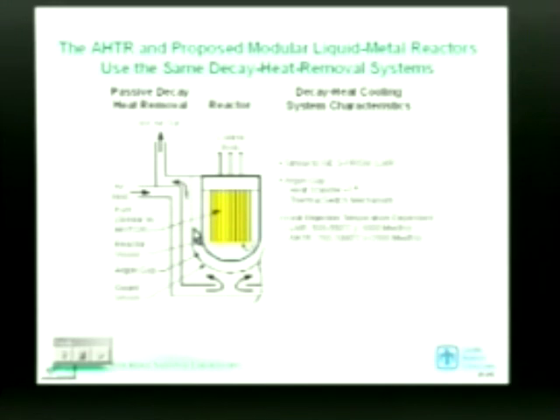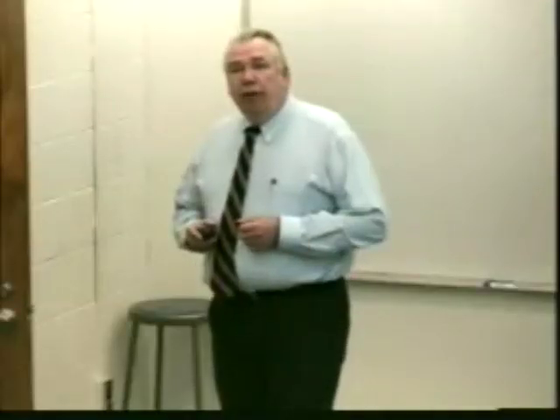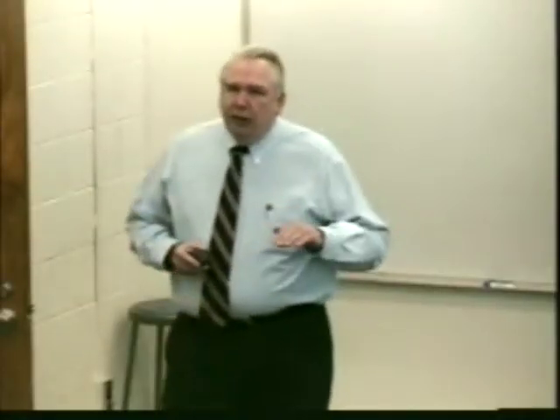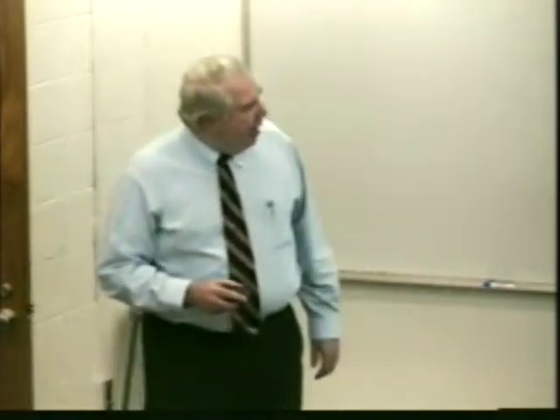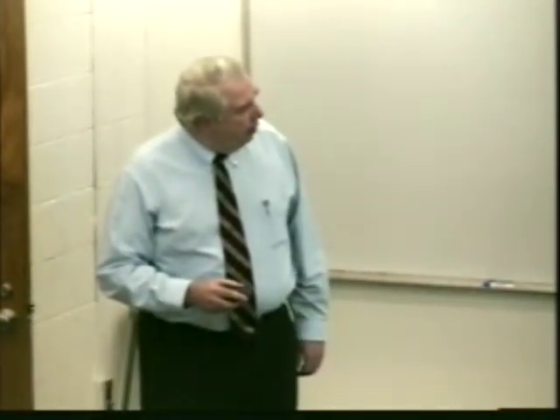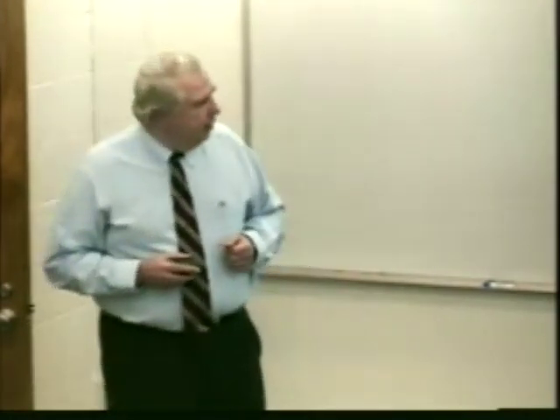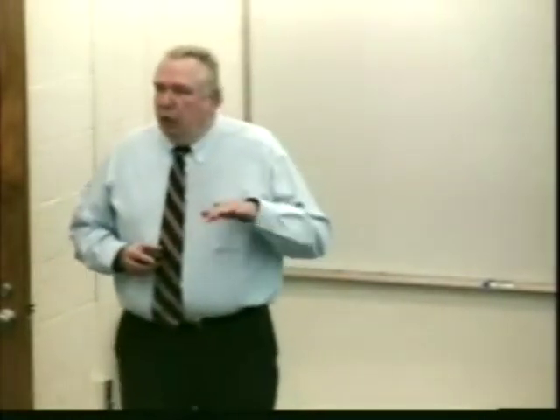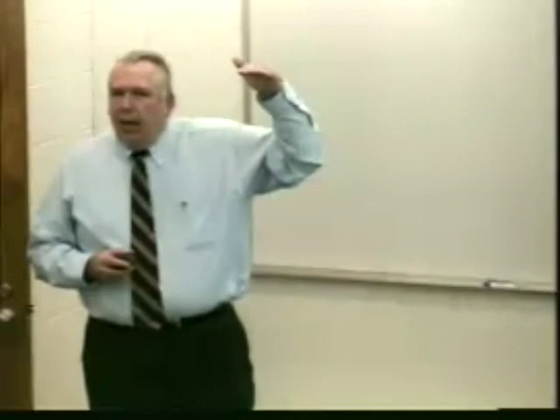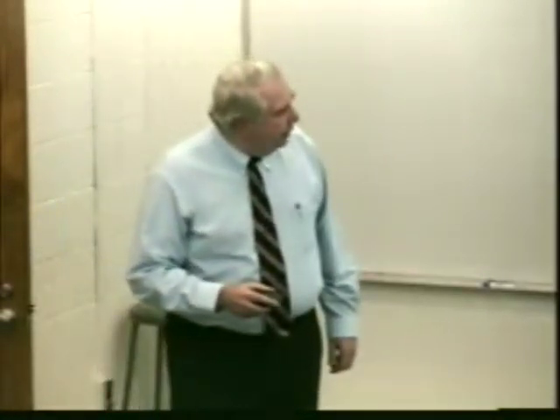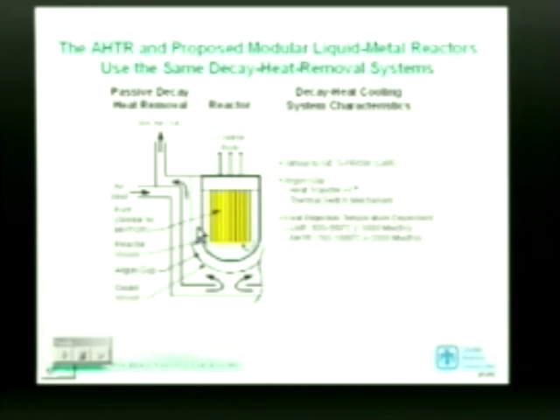It's sort of like a sun lamp. Go put something under a sun lamp. Same philosophy. Now, what's important about heat transfer by radiation is that the amount of heat you transfer depends upon the temperature to the 4th power. So a very small increase in temperature results in a massive increase in the amount of heat that goes from the primary reactor vessel to the secondary reactor vessel. It's a solid state thermal switch mechanism. Low heat loss at one temperature, very high heat loss if the temperature goes up 50 degrees C. And of course, people have worked out the details of this for the prism reactor of General Electric.